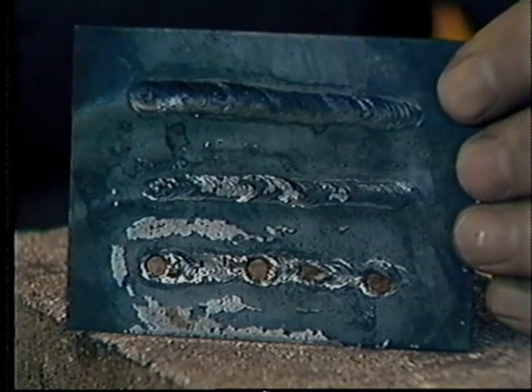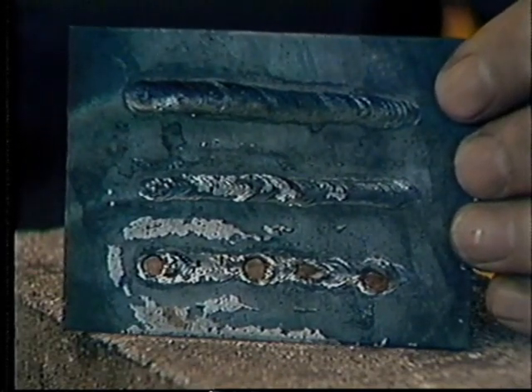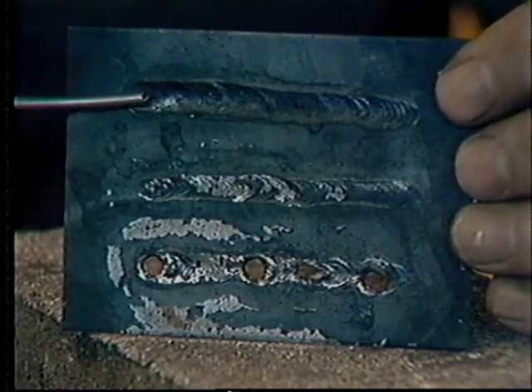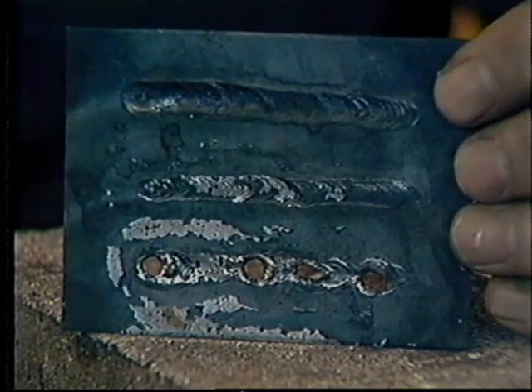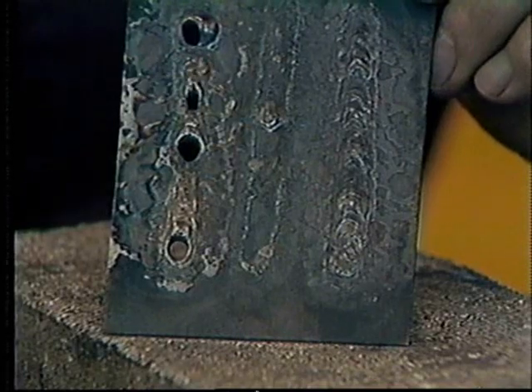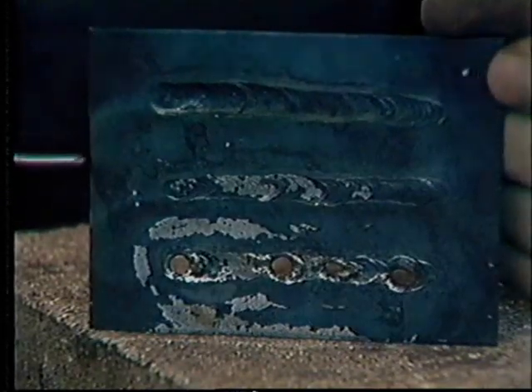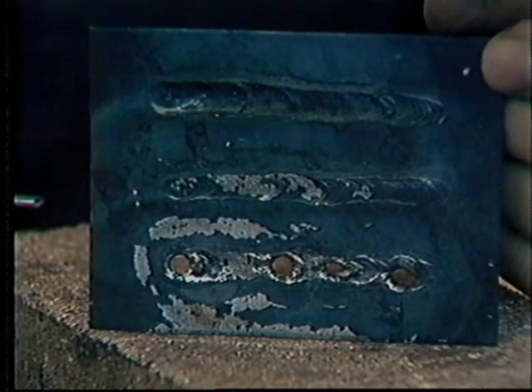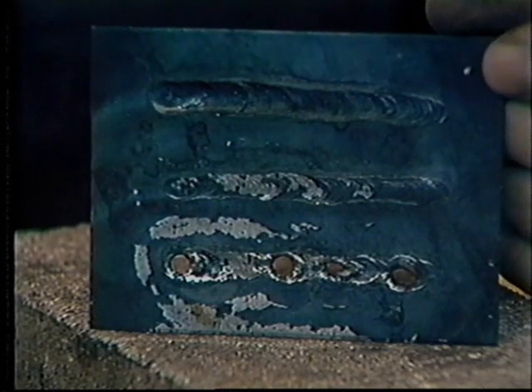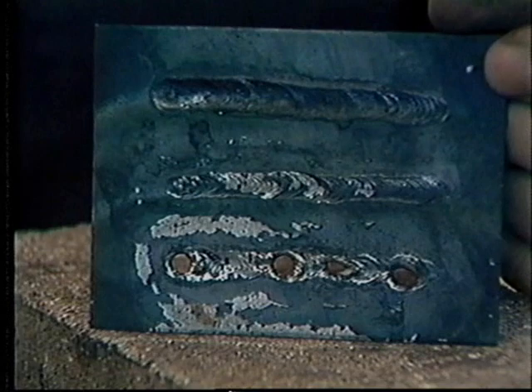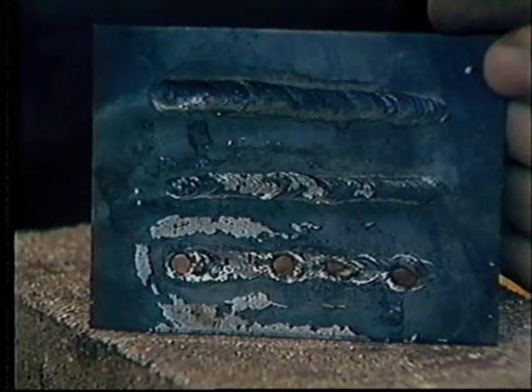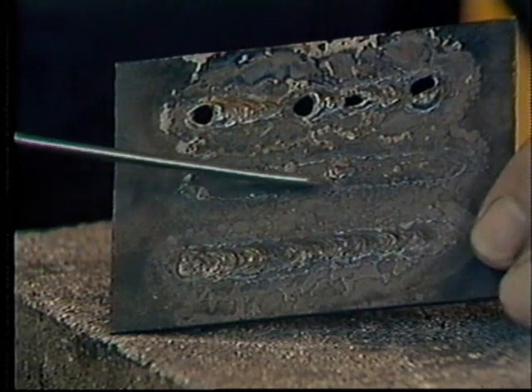Now, it appears that there's something wrong in this one. The top bead is a good bead. It was run properly. It has even penetration onto the back surface and appears to be a good bead. What's wrong with the middle one? The second bead was a result of lack of penetration. He didn't get enough heat into the puddle, and as a result did not penetrate clear through. And you can see there's no penetration through that back surface.